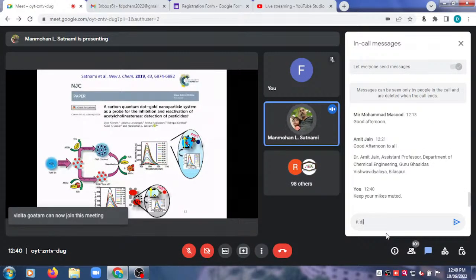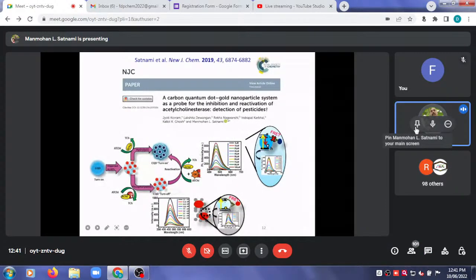Okay, on the other side, what did we do? We took carbon quantum dot, we added gold nanoparticle, fluorescence quenching happened, then we added acetylcholinesterase the same way, then we added acetylthiocholine, then after this we added organophosphorus pesticide. So organophosphorus pesticide will inhibit the activity of acetylcholinesterase. Then the process in the upper end of this figure will not happen. So what will happen? The fluorescence quenching will continue. Then further we added reactivator, oxime reactivator. The inhibited acetylcholinesterase enzyme is reactivated and it starts functioning.